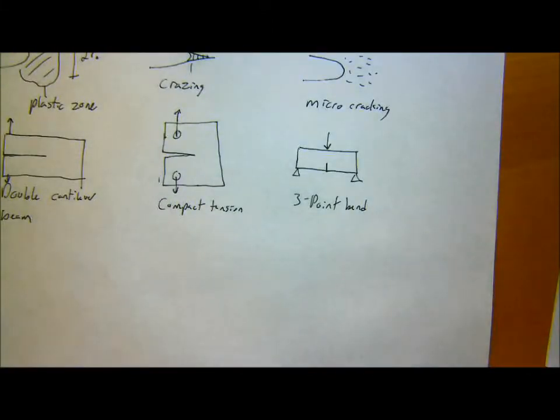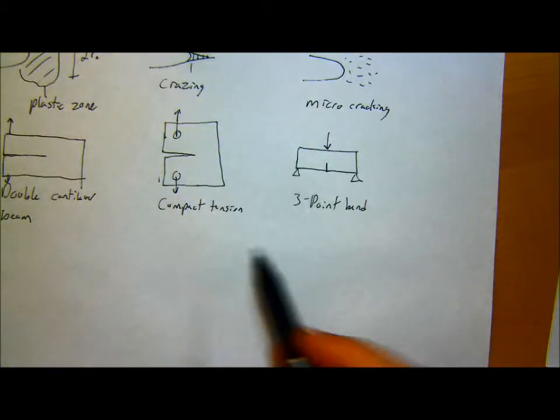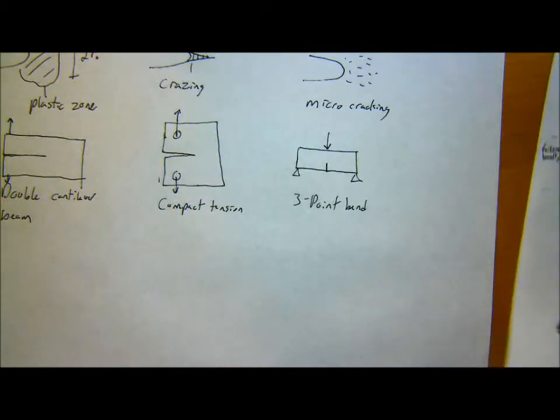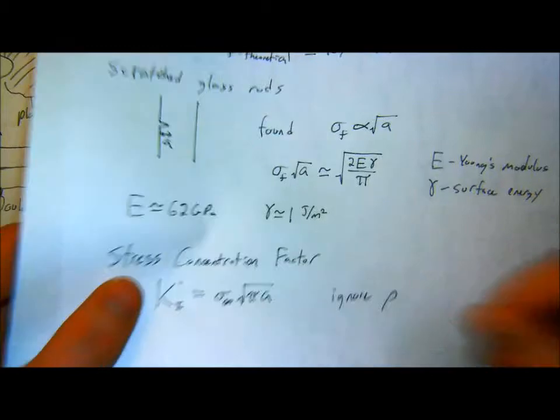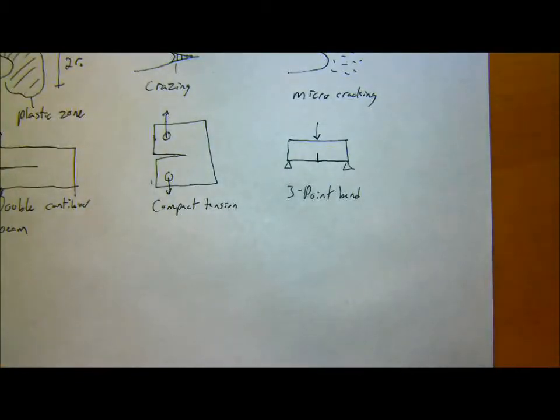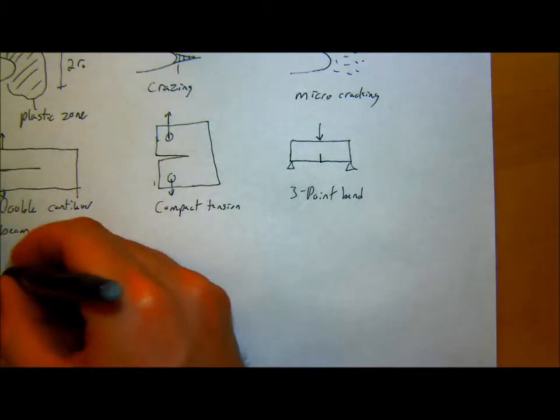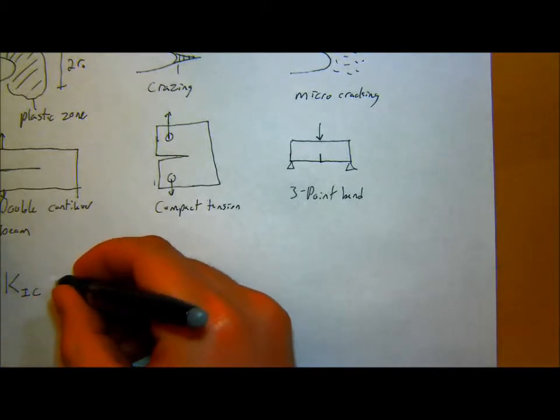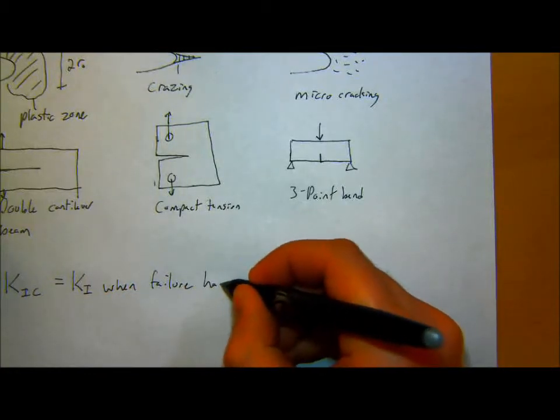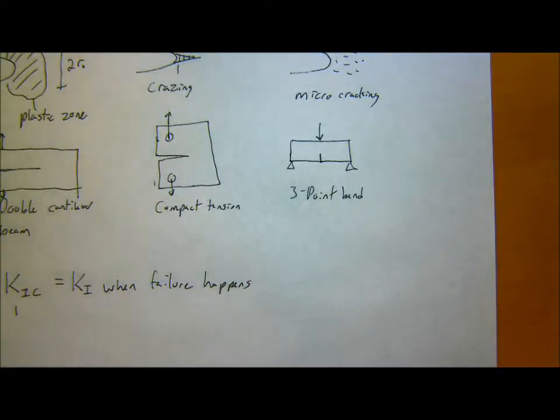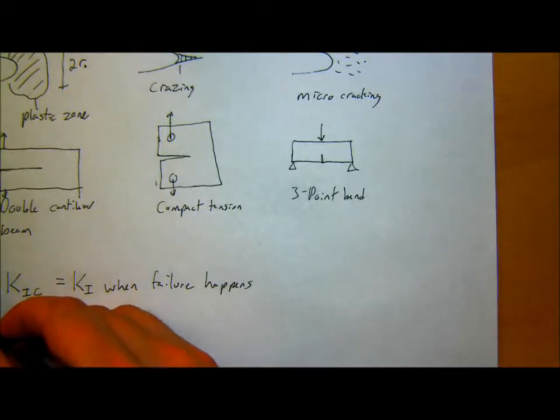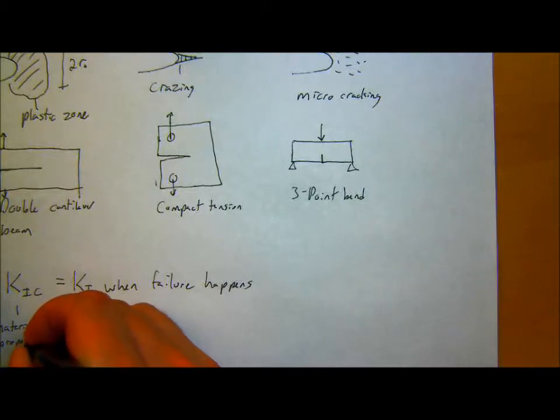Technically now, we defined some K1 as a stress concentration factor that's a function of geometry. Now, the question is, when does our material actually fail? So for that, we define now a K1C equal to just the K1 when failure happens. So K1C now, we're going to call our material property, and this is from geometry. So what this means now for a given material, there's a couple ways to think about it,